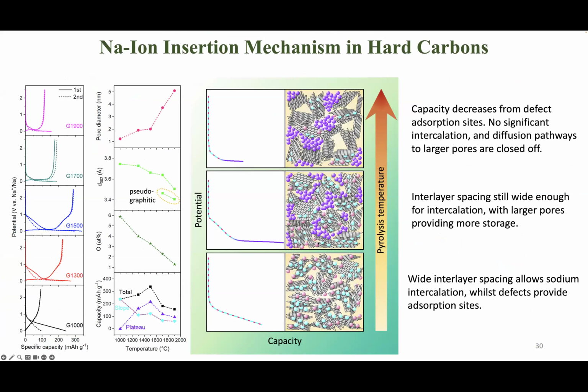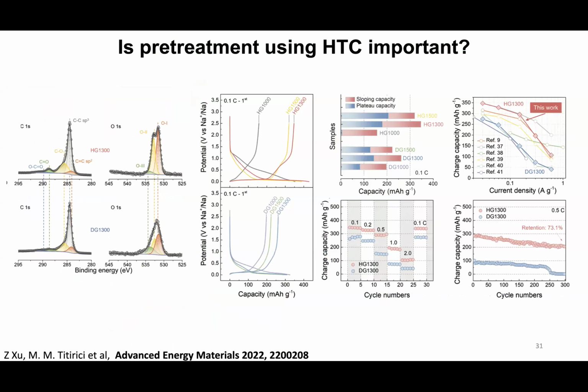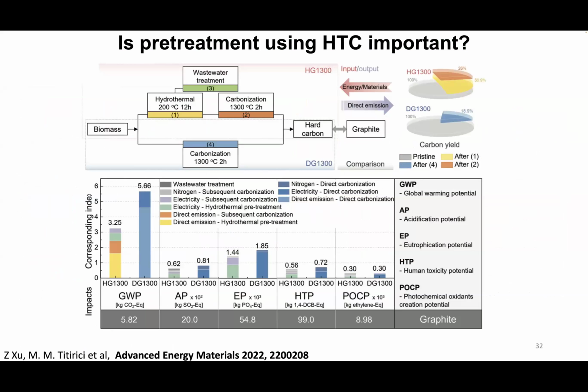And we came up with the fact that if you want to have an ideal hard carbon, you need to have the right interlayer spacing that allows sodium to go to your closed pores where sodium is plated as a metallic plating. And the plateau comes from the plating of the sodium, and the slope comes from mainly interaction of your sodium with the defects of this carbon, but some degree of intercalation. And by understanding all of this, you could fine-tune your materials to get the ideal material.